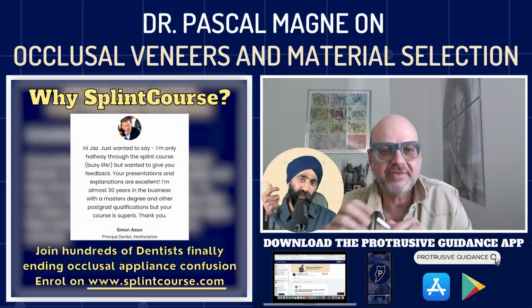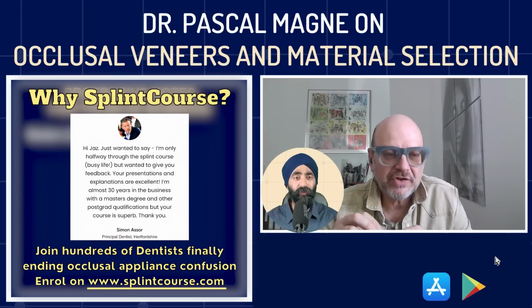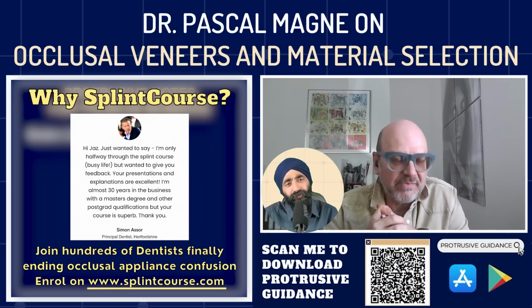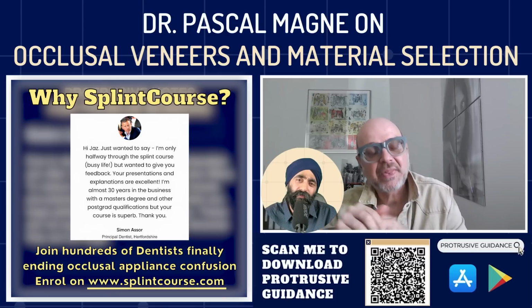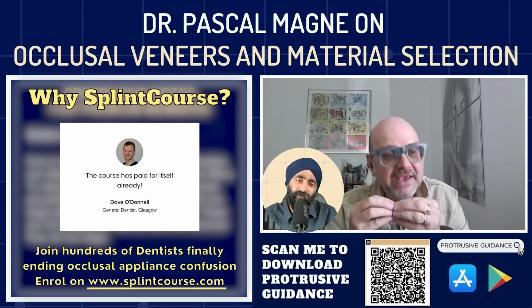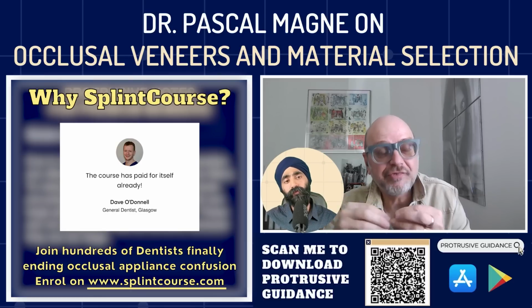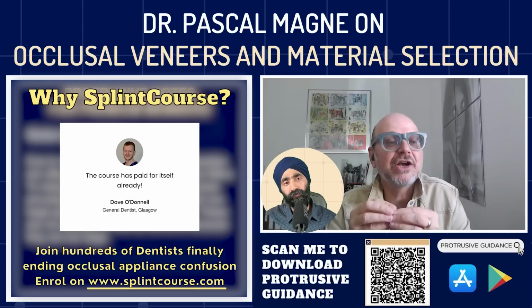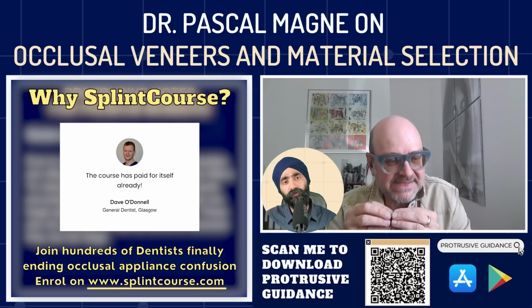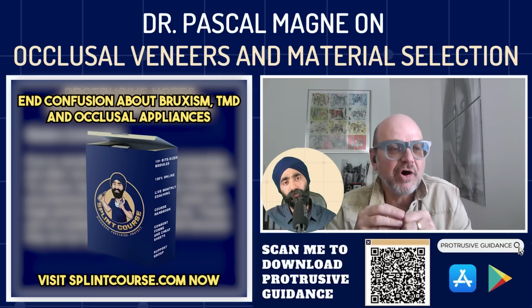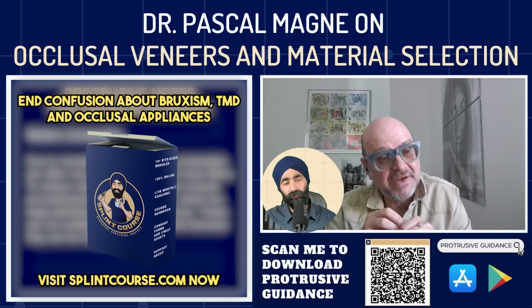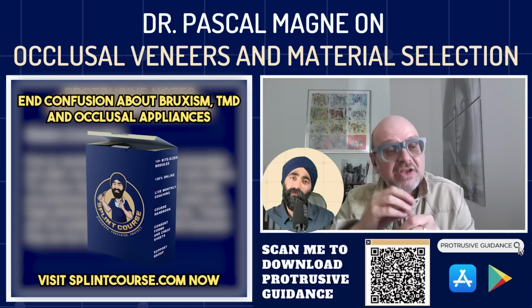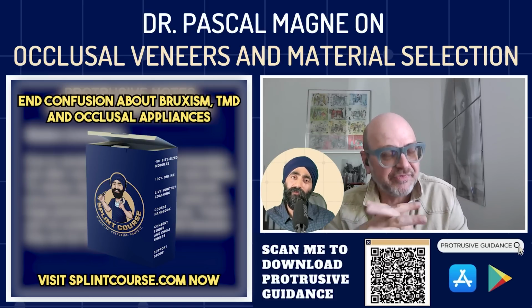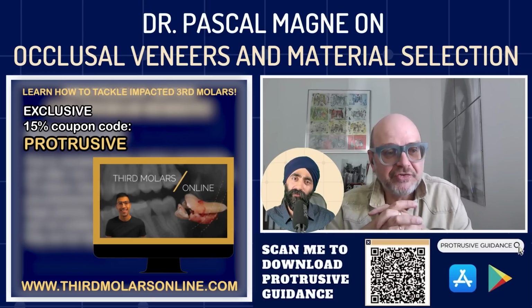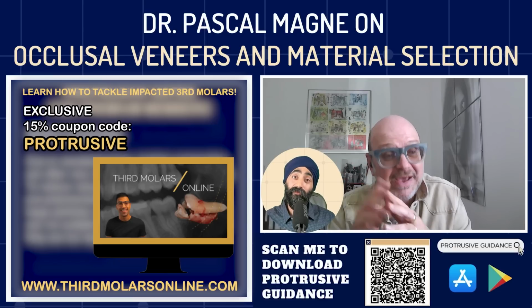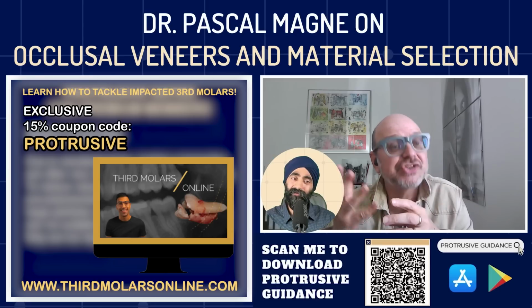And can you give an example of which composite to use? Because not all those composites are created equal. And the problem today is because of the nanotechnology, the nano fillers by themselves make composites very viscous. And in order to fight that problem, manufacturers have to include pre-polymerized filler complexes in the material. Those are bigger chunks of composite. It's made of the same filler, but it's pre-polymerized, ground, and included to decrease the viscosity of those highly filled nano hybrids. Those pre-polymerized fillers can be very big, up to 20, 30 micron. Those materials will never work as a cement because those chunks are too big, right?